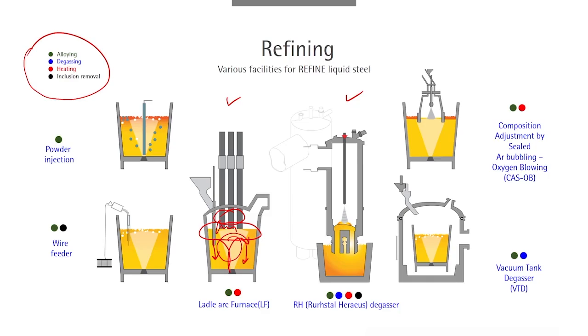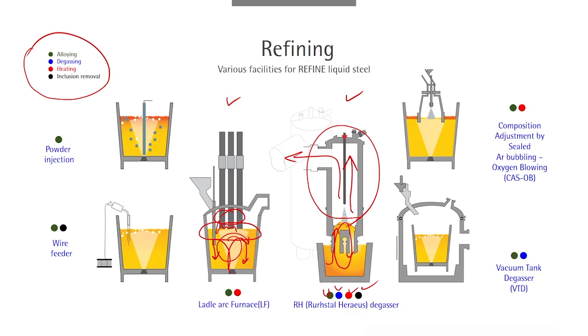On the right-hand side, we see the RH degassor. Its most important purpose is degassing. The upper part is connected to a vacuum pump, making the inside chamber a vacuum. Liquid steel is circulated through this route, and gaseous elements like nitrogen or hydrogen are evacuated into the chamber. If we want to decrease carbon level, carbon forms CO gas which is also evacuated. This facility also homogenizes liquid steel through circulation.